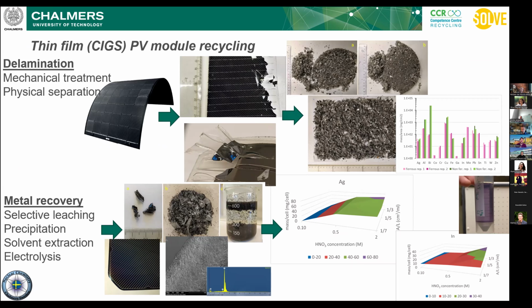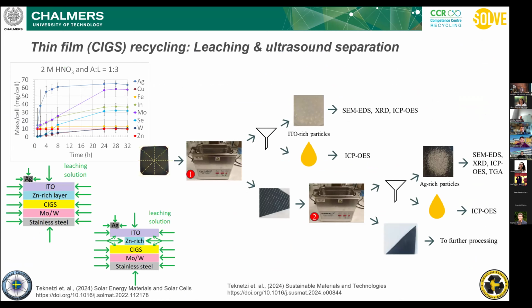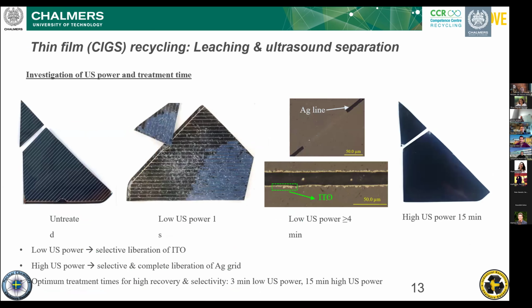Of course, an important part is the delamination of the cells, and then we focus on different approaches. One of them is leaching with different acids. But when we come to standard leaching, we realize that because of its layered structure, we can selectively remove some layers. With the implementation of ultrasound power, we can remove the specific layers step by step, which are ITO and silver. Step by step analyzing the ultrasound power, we can clearly see that by removing the down layers, in the first step we can remove the ITO, and in the next step, we can remove the silver.